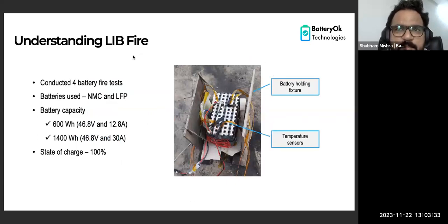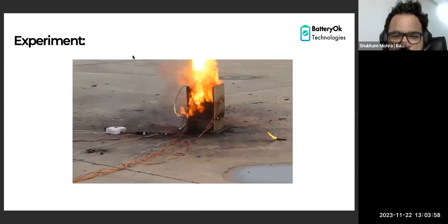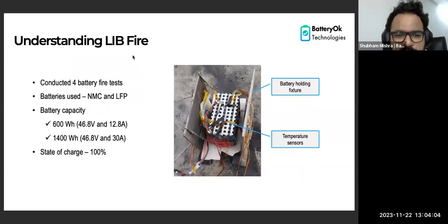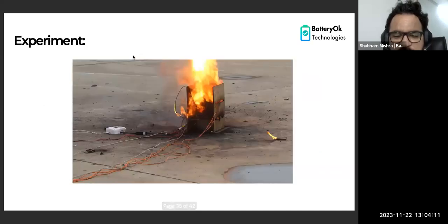We have conducted some lithium-ion battery tests for getting the data of lithium-ion battery chemistries. We have put some thermocouples inside the lithium-ion battery pack and done the thermal runaway test, and during the test we found some interesting insights, which I'll share. On the right side, you can see the lithium battery which is burning. It has a spec of around 48 volt and 30 ampere hour. And on the left side, you can see the prototype version of EV Doctor, which was getting the data during the thermal runaway.